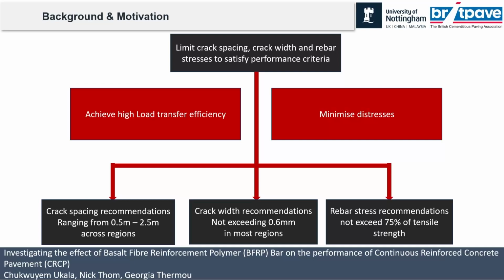Different countries or different regions have their limits. We get a design to limit the crack spacing, and also to limit the crack width to maybe about a maximum of 0.6 or 0.5 mm. The importance of doing that is to limit the ingression of materials that could end up affecting the steel or maybe the base of the CRCP. Also, we try to keep our rebar stresses at somewhere around 75% to avoid some level of rupture that could take place in the member.